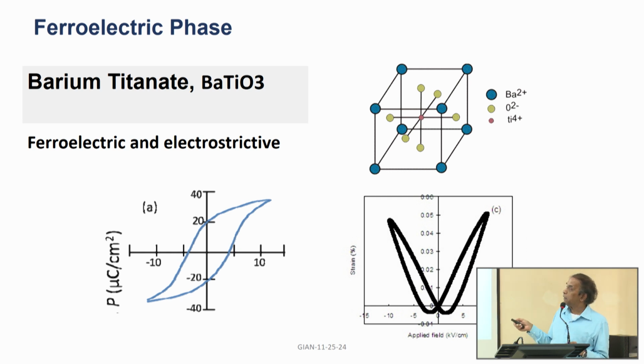For barium titanate, it has a cubic structure above the ferroelectric transition. So, when it goes through the ferroelectric transition, the barium is slightly displaced, so that the centers of positive and negative ions have a separation. That will produce a dipole moment, and that is how it becomes a ferroelectric.